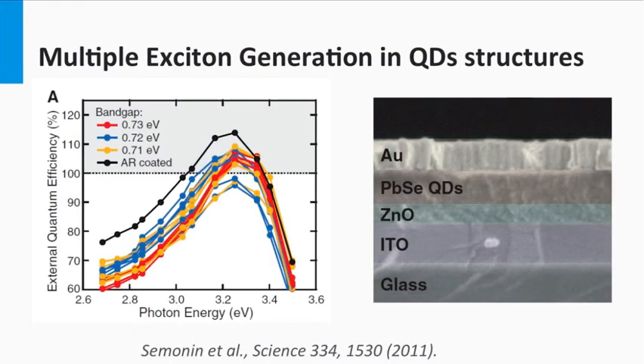Here we see the results out of a paper of Semonin demonstrating that an EQE of above 100% can be achieved. The absorber layer contains lead selenide quantum dots, and in the blue region from 3.1 up to 3.4 electron volt, the quantum dots realize an EQE above 100%. The challenge is to move this spectral response to lower photon energies, as the solar spectrum contains far more photons in this spectral range.